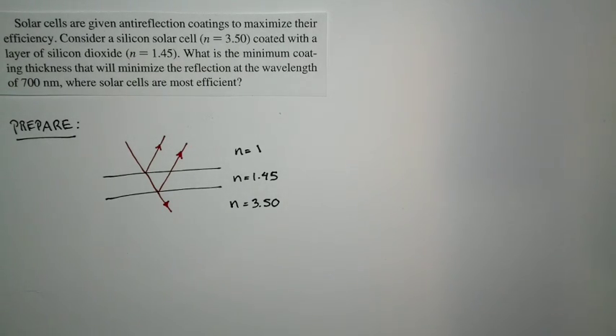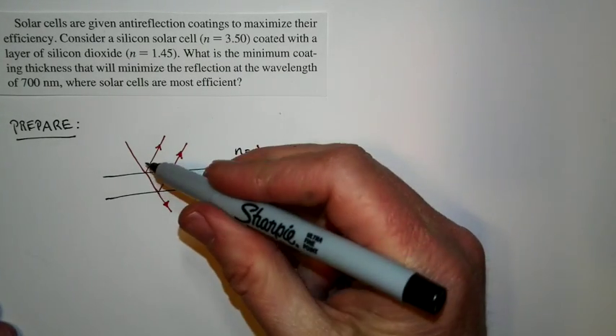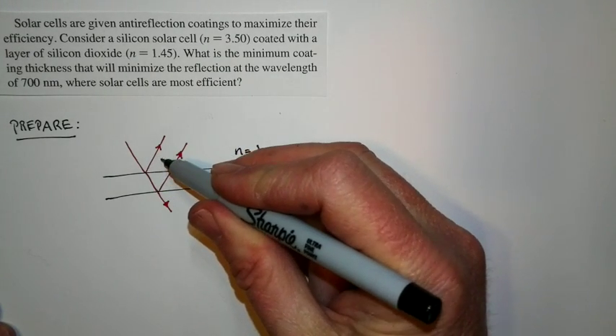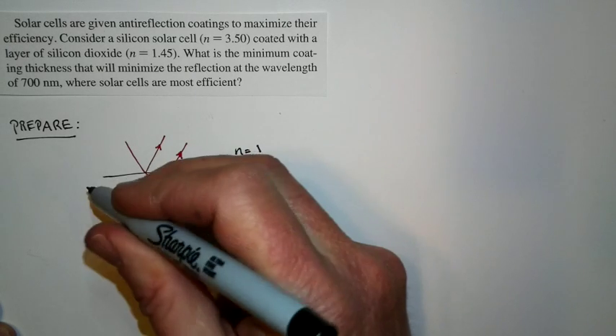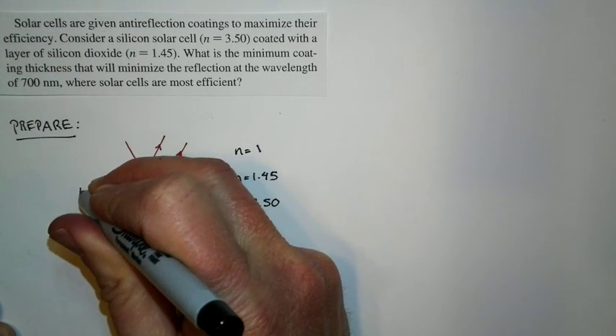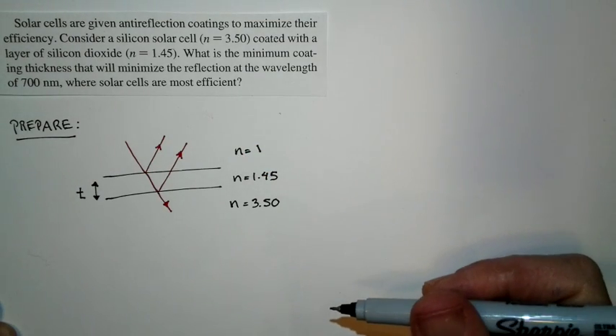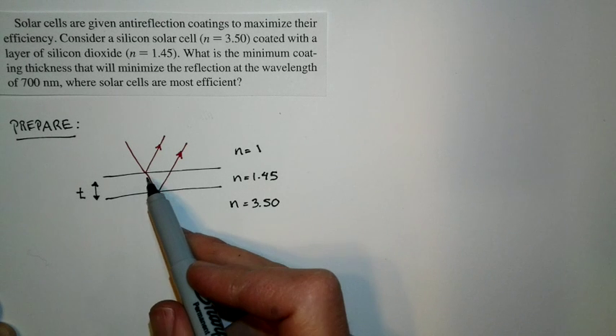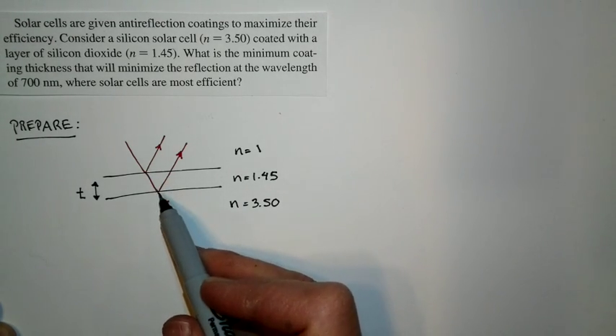Now here's the thing. In order to arrange it so that I have destructive interference between these two beams of light, I need to have a certain thickness of coating. So we'll say this has a certain thickness, T. There's a phase change at this boundary. There's a phase change at this boundary.